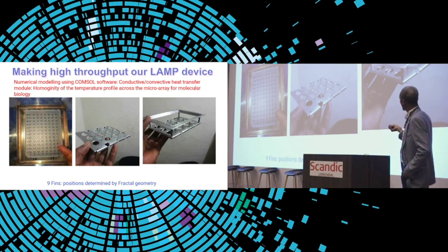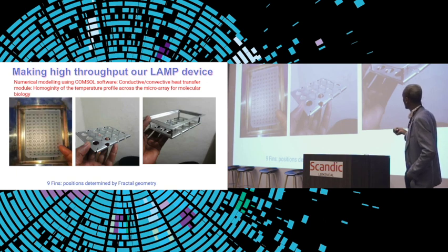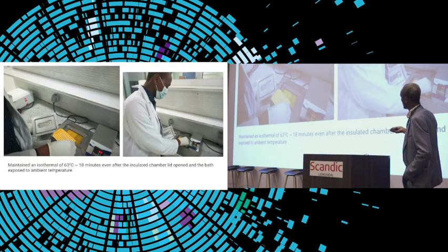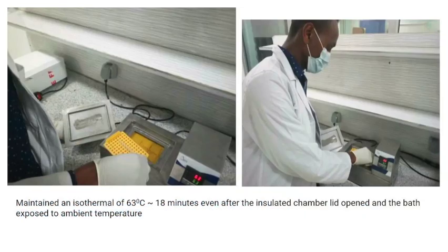As you can see, the heat is supplied just below. This is the heat supply, and the wax is deposited here, and with the fractal geometry one can ensure the uniformity of heat transfer. On top of this, we put our assays to test it. This maintains an isothermal, constant temperature for 18 minutes, even after the insulated chamber lid was opened, and we tested it for COVID.